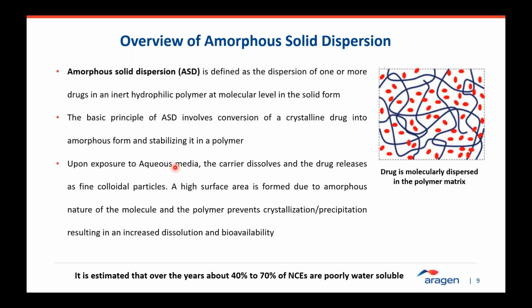When this solid dispersion powder, or the capsule or tablet made from it, is exposed to aqueous media in the GI tract, the carrier dissolves first and the drug releases as fine colloidal particles, still in amorphous state, forming a very high surface area and rapidly increasing the dissolution rate. The drug is surrounded by polymer solution, which prevents crystallization or precipitation of the drug, thereby improving bioavailability. So the extent of supersaturation and inhibition of precipitation determines how much improvement in bioavailability can be achieved in vivo.